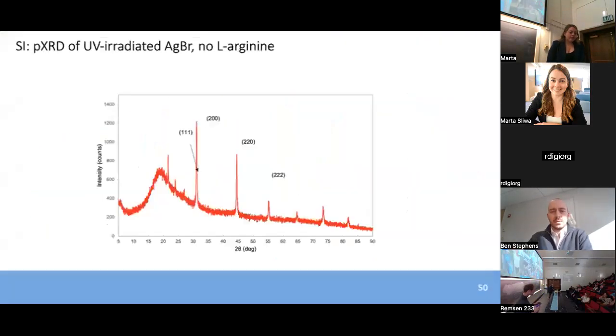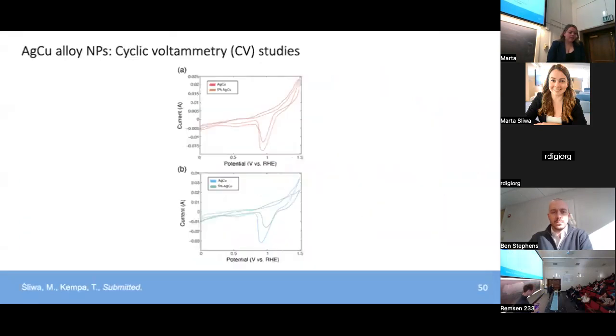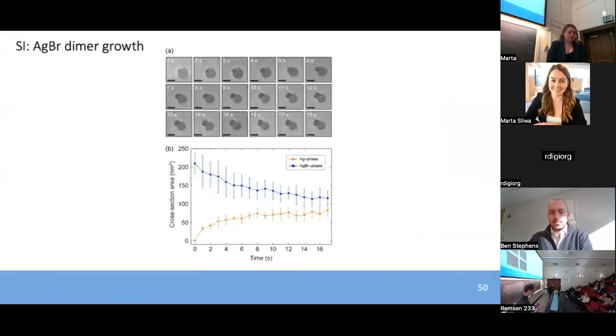There absolutely is. I do have some data right here. As we grow that silver bromide dimer, there is a slight contraction of the silver bromide phase, especially when it goes from that cubic morphology to that spherical morphology, and then the growth of the silver phase of the dimer. But at the end of that process, they are roughly the same size. There's only about a 2 to 5 nanometer discrepancy between their diameters. If we continue to irradiate them, the silver continues to nucleate out, and then the silver bromide actually totally contracts and disappears, and we get this sort of silver rod-like structure, which I can show you if you want to see. Yeah, absolutely.